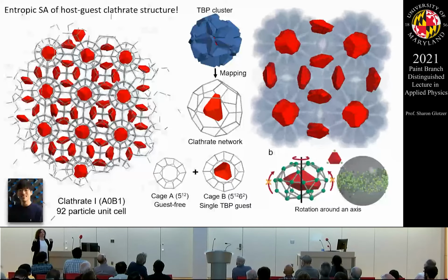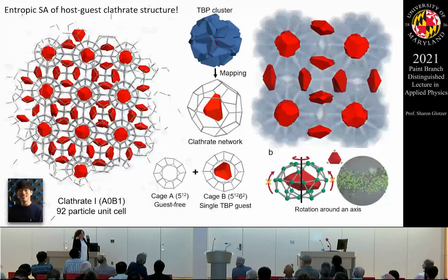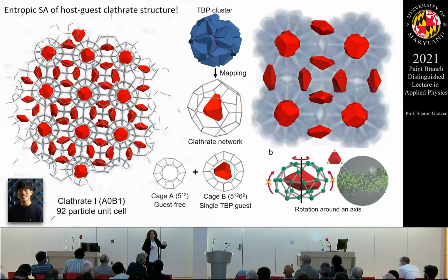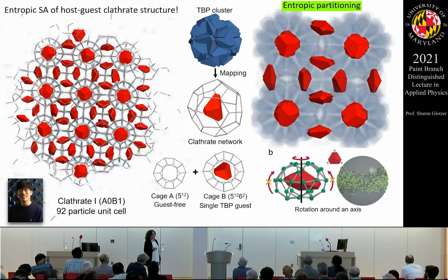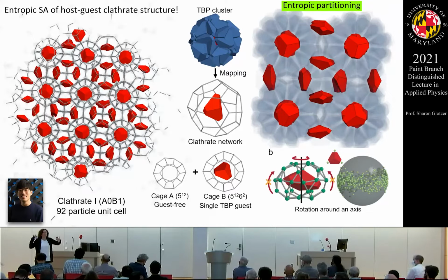If you take them out, the host crystal spits out one of its own to put back, to give a particle up to give the system entropy, to stabilize, to minimize the free energy of the system. So this is just amazing. It's a kind of entropic partitioning or entropic compartmentalization, where the system has sacrificed part of itself, and then the rest of it is able to stabilize it.